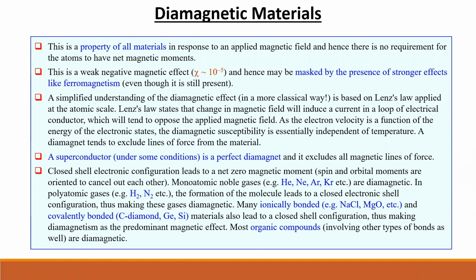A simplified understanding of the diamagnetic effect is based on Lenz's law applied at the atomic scale. Lenz's law states that a change in magnetic field will induce a current in a loop of electrical conductor, which will tend to oppose the applied magnetic field. As the electron velocity is a function of the energy of the electronic state, the diamagnetic susceptibility is essentially independent of temperature. A diamagnet tends to exclude lines of force from the material. A superconductor under some condition is a perfect diamagnet, and it excludes all magnetic lines of force.